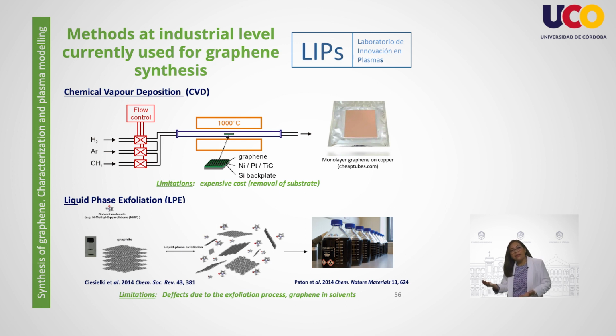On the other hand, liquid phase exfoliation is a top-down technique using graphite as a raw material and producing high quantities of multi-layer graphene structures. This technique is more affordable than CVD. However, the material presents a high presence of defects and implies an environmental challenge because of the use of solvents in the process.